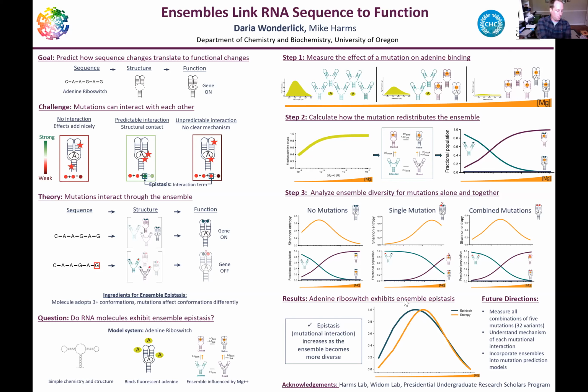Okay, so my preliminary results from the 2 mutations I've measured suggest that the RNA system does exhibit ensemble epistasis. So if the ensemble is the mechanism of mutational interaction, then epistasis should be highest when the ensemble is most diverse. And this correlation is exactly what I see when I overlay the epistasis between the 2 mutations in blue with the ensemble diversity in orange. So I'll wrap it up there.